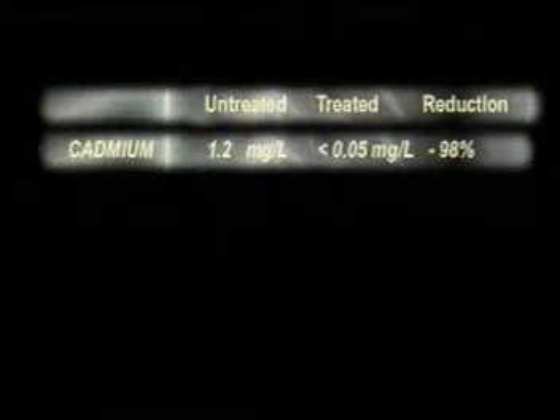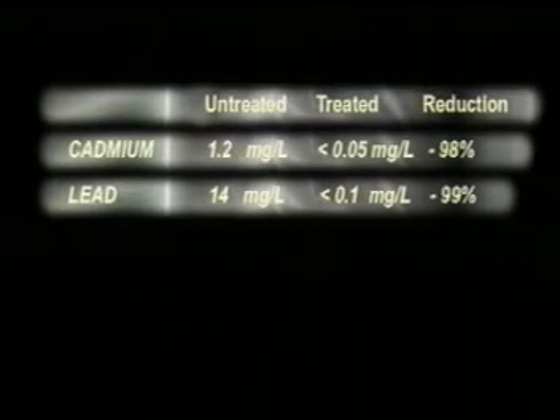Prior to stabilization, cadmium was measured at 1.2 milligrams per liter. Post-stabilization levels were less than 0.05 milligrams per liter. A 98% reduction of leachable cadmium was achieved. Prior to stabilization, lead was measured at 14 milligrams per liter. Post-stabilization levels were less than 0.1 milligram per liter. A 99% reduction of leachable lead was achieved.